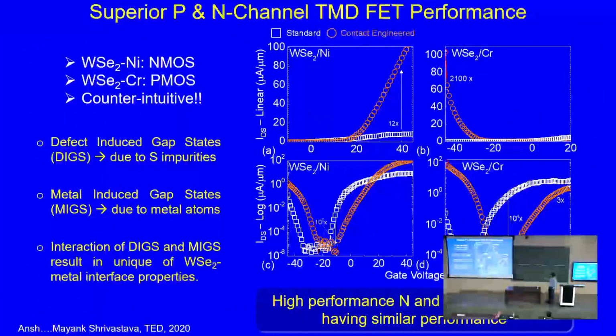And the reason for this threshold voltage shift is that in this case we did this sulfur introduction across the entire channel. So wherever there were these sulfur defects, the sulfur goes and sits on those defect sites, right? So it passivates the defect, it basically brings the Fermi level down to the intrinsic level in the channel, and the contact, since we are also putting metal on top of it, introduced those donor or acceptor states depending on the metal, forming the N-type and P-type transistor, right? So the channel became intrinsic, resulting in positive or negative threshold voltage depending on the nature of the contact.